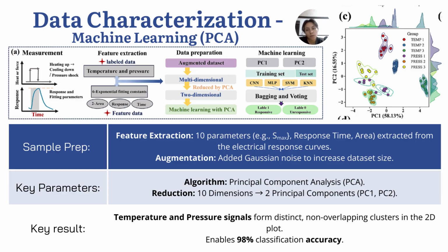10 features were extracted from the electrical response curves, including maximum response and area, and Gaussian noise was added to expand the data set and improve variability. After that, principal component analysis was applied to reduce the original 10-dimensional data into two principal components. This transformation created a clear separation between temperature and pressure signals in the 2D space, forming non-overlapping clusters and enabling a classification accuracy of 98%.